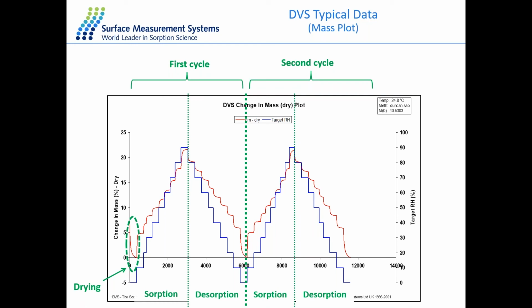And sometimes it's very interesting to study this kind of drying effect at different temperatures, as well as different degrees of drying. And it's a two-cycle experiment with both sorption and desorption. And you can see the second cycle is exactly the same as the first cycle. That means there is no irreversible change along with the process. It's a perfectly reversible process. And this is the mass plot, the change of mass as a function of time.